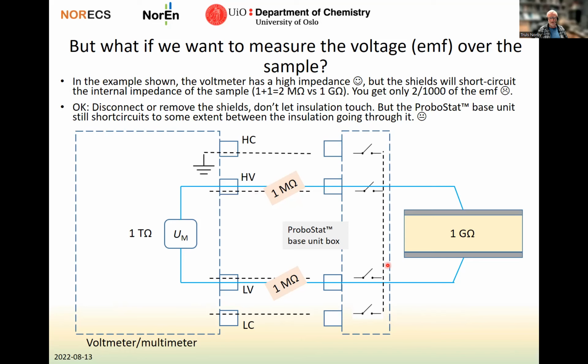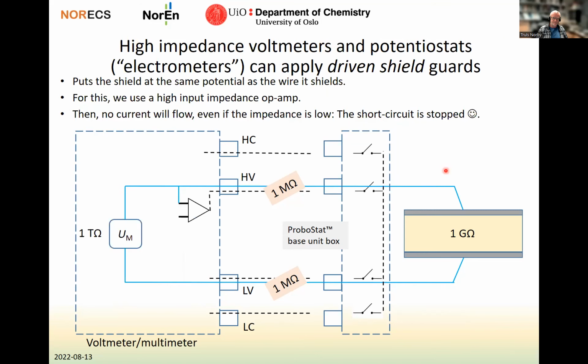But inside the ProboStat, we have already the problem that the metal base unit of the ProboStat is a kind of a short circuit between the insulators that go through there. So you have maybe some mega ohm there, and that is then a problem, not for the impedance measurement, but for this voltage measurement. So what can we do about it? Then we come to high impedance voltmeters and potentiostats, which are then called electrometers, can apply driven shield guards. And by applying this, they operate as if they had infinitely high impedance. And that's why they are called electrometers, because they behave like old days electrometers, which was purely capacitive.